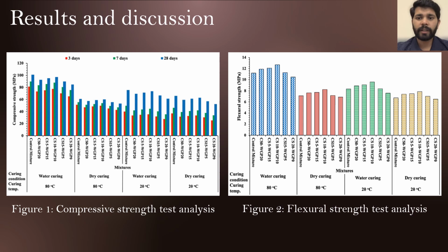Figure 2 shows the flexural strength of all specimens under all curing types. It is evident from figure 2 that flexural strength is increased up to 10% replacement of Cenosphere and found maximum at 10% replacement of waste glass and Cenosphere and then gradually decrease. This pattern is prominent in all curing types. Flexural strength increment is because of higher pozzolanic activity of Cenosphere and waste glass powder and tightened bonding between the particles. Secondly, the pronounced bending resistance of Cenosphere is because of the presence of high aluminosilicate constituents that provide huge energy absorbing and dissipating properties leading toward the increased flexural strength.